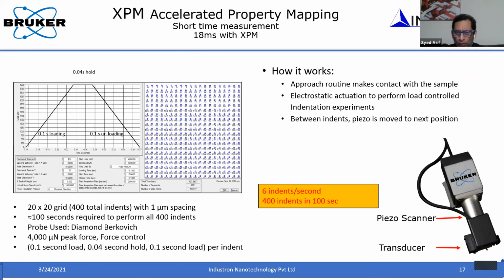For example, you can do this indentation to a higher depth, where you can induce plasticity along with the elastic deformation. If you can also measure the elastoplastic deformation, then you do it in a very rapid way. For example, if in 1 second you can do 5 or 6 indents, that is pretty fast. In that way, you can have hundreds or thousands of indents within a minute, and then you can process the unloading curve, get the load displacement response and stiffness, and calculate the hardness and modulus at different grid positions. In that way, you can also construct a map.